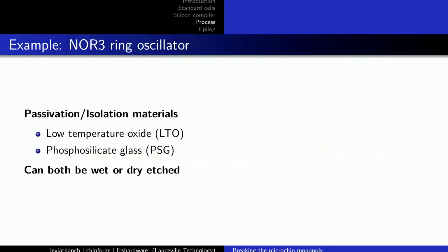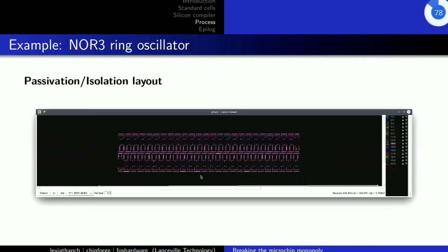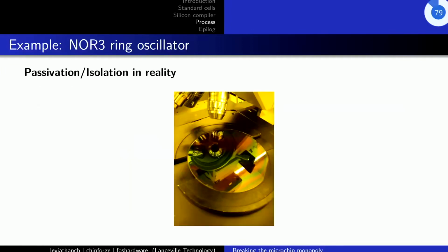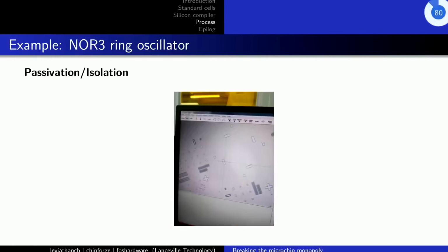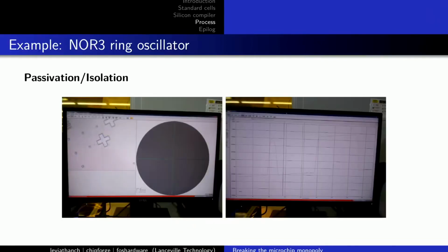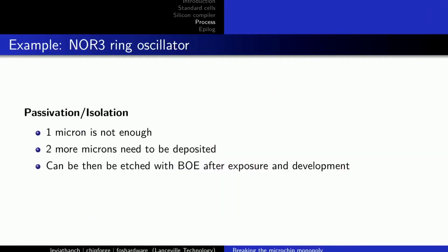I skipped that one, that's just really interconnect. But I plan to make videos soon where I go through results, like a daily video blog. Just so you see, the oxide, depending on the angle, has different colors. So that's LTO, the isolation. And then you see our topological measurement device. You see this 1 micron, because we only deposited 1 micron for now. You see the height differences, and we see that 1 micron is not enough. So we still have these sharp edges, which we don't want. When I'm back in Hong Kong, I have to deposit another 2 microns.